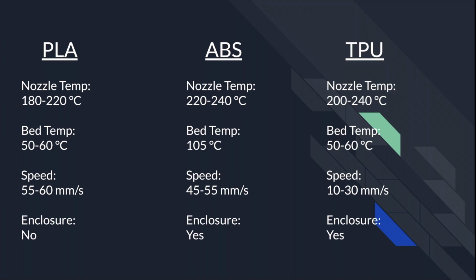So again, different filament requires different printing parameters. So for PLA, you want to print between 180 to 220, a bed temp of 50 to 60, and a speed of 55 to 60. For ABS, since this is a harder material, you want a nozzle temp between 220 and 240, a bed temp of 105, and a speed between 45 and 55.